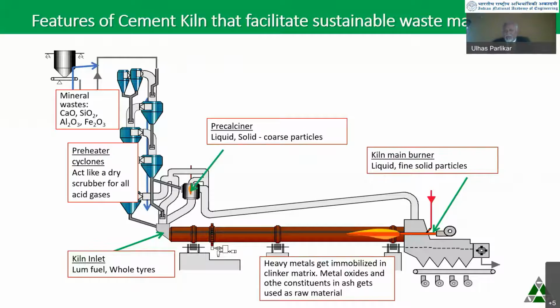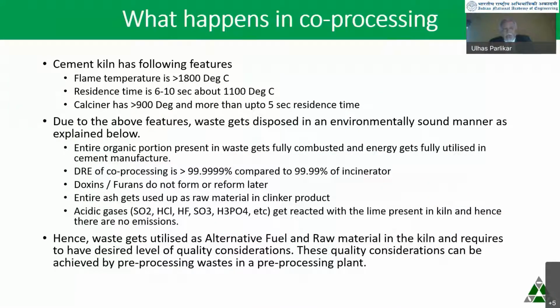And if you look at waste streams, they can be solids, they can be gases, they can be liquids, and they can be sludges. So all these kinds of waste materials are amenable for feeding into the cement kiln, and that's the beauty of the cement kiln that we are talking about. Now, I already told you that the flame temperature is more than 1800, up to 2000 degrees centigrade, and the residence time is 6 to 10 seconds, at about 1100.